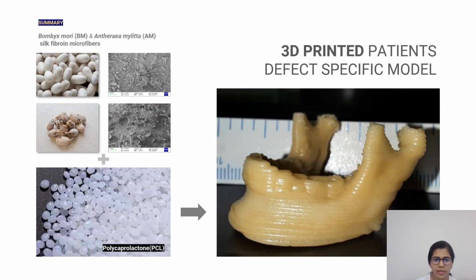So, to summarize, we have obtained both the silk variants, Bombyx mori as well as Antheraea mylitta. We have formed one single protocol to form silk fibroin microfibers via a process of degumming and alkali hydrolysis. And then we have mixed them with PCL to form the composite, and we have optimized all the 3D printing parameters to successfully print the patient defect specific model.